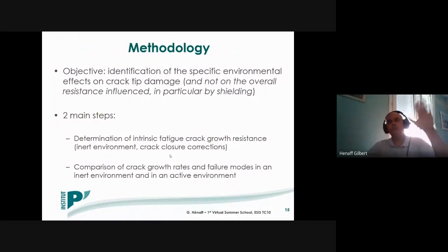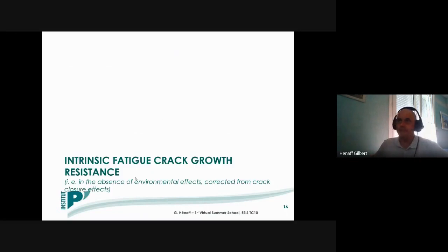And for that, we will proceed along two main steps. First, we will have to determine the intrinsic fatigue crack growth resistance. That means in an inert environment and after crack closure corrections. And then by comparing the fatigue crack growth rates obtained in an active environment such as ambient air and in an inert environment, but also by comparing the fracture surfaces, we will get insights into the mechanisms operating at the crack tip. So let me say a few words about what I mean by intrinsic fatigue crack growth resistance.